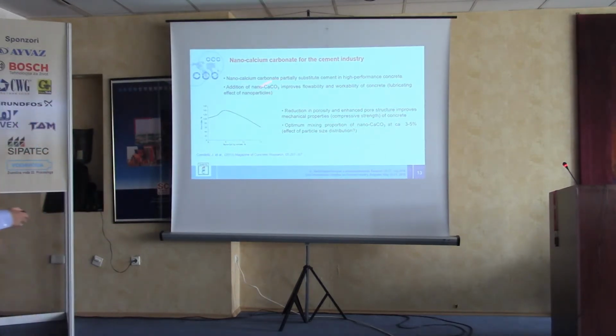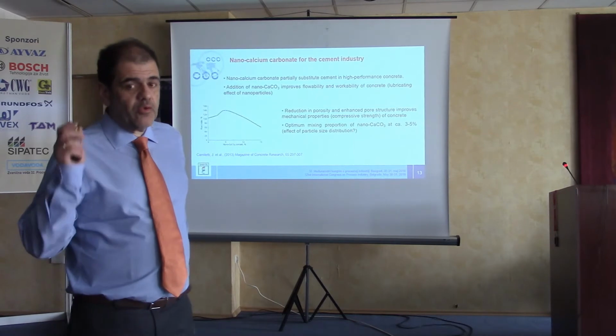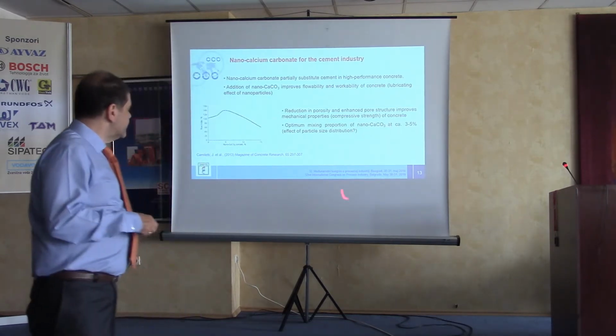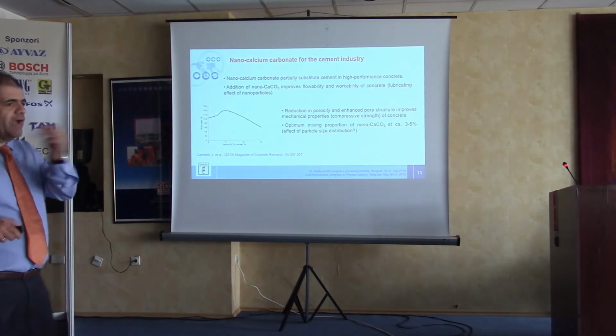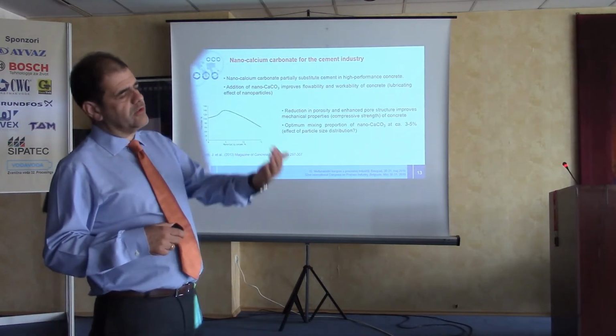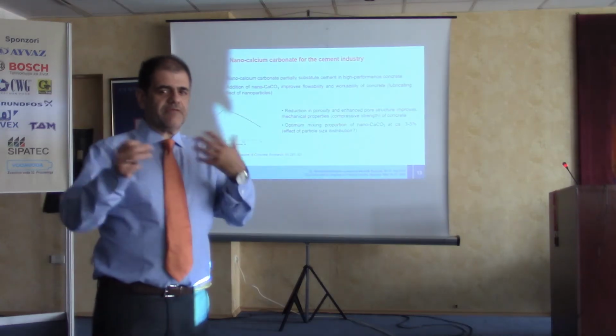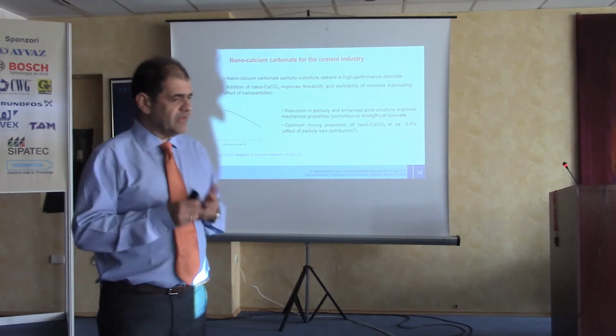Now, of course, why do you need nanoparticles? Because nanoparticles can improve the quality of cement, the quality of concrete. But, of course, as always, you need to be careful, because if you put in too many nanoparticles, or if you put in too fine nanoparticles, then the quality goes down. So again, it's a very careful matching of the sizing and distribution of the sizes of the particles.